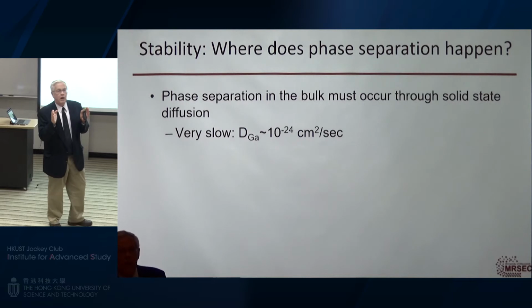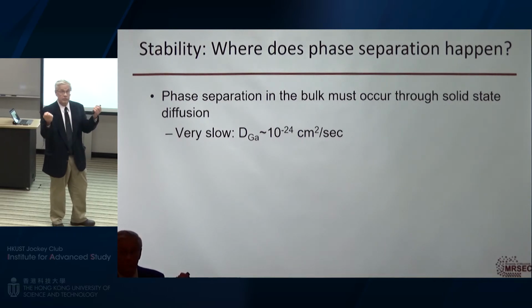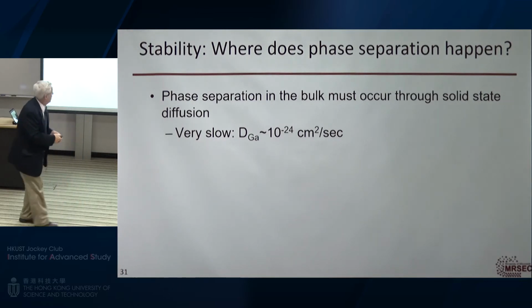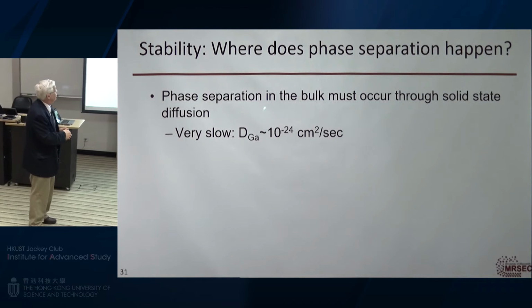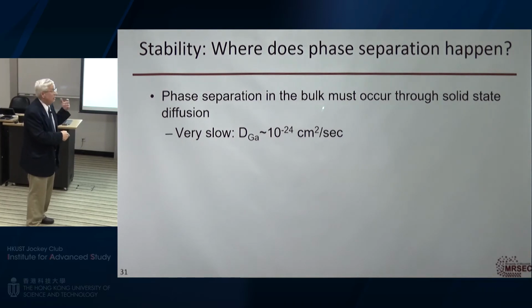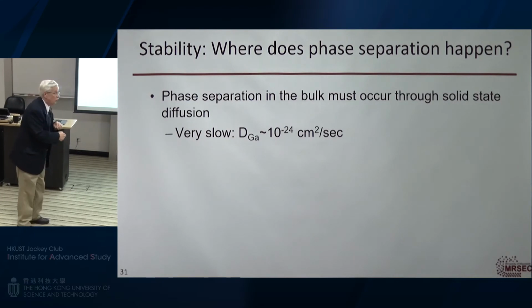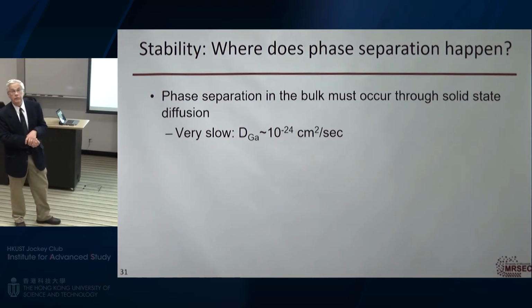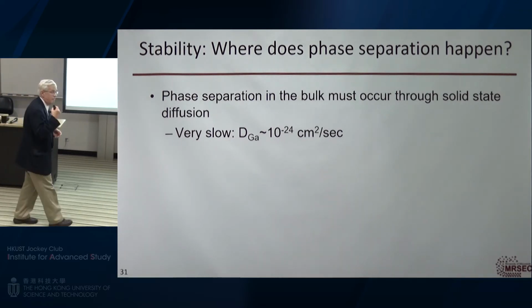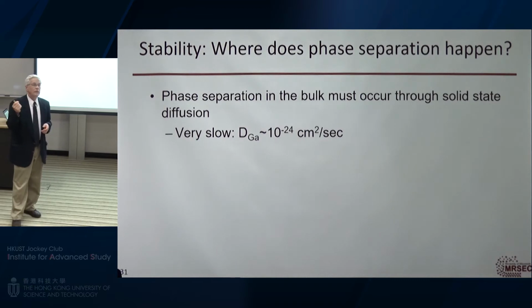For it to fall apart, for it to phase separate, to reach equilibrium, things have to diffuse inside the solid. And phase separation after I make it can only happen through solid state diffusion, which is incredibly slow near room temperature. Atoms don't move around inside solids very easily. And so if I could make it, it actually is stable and usable.